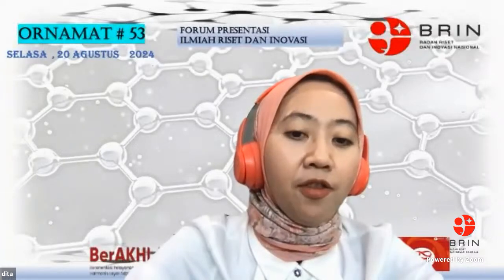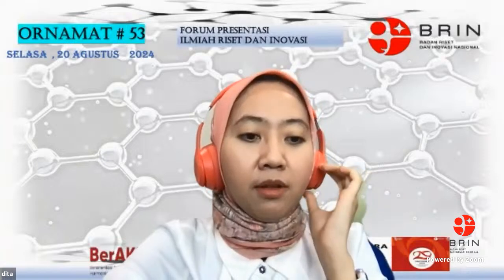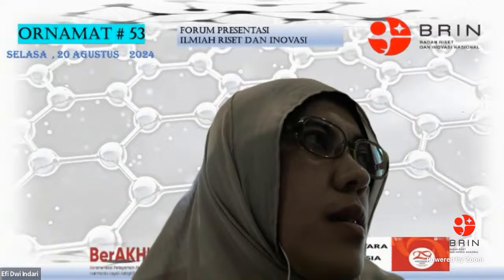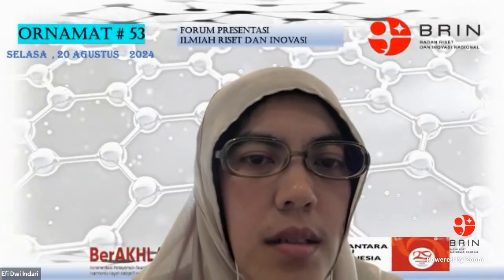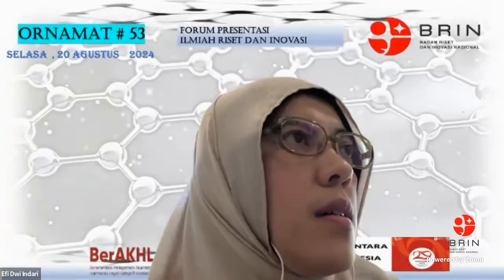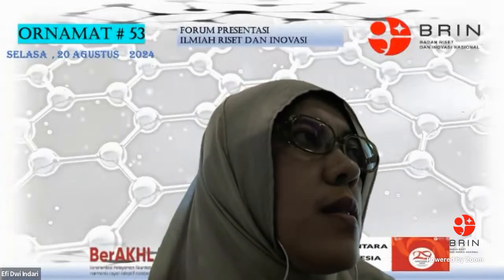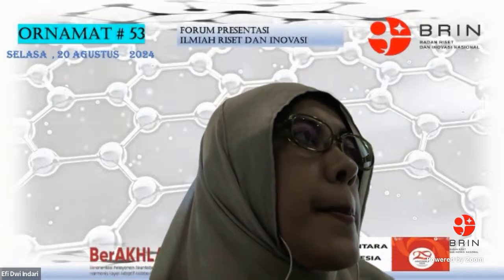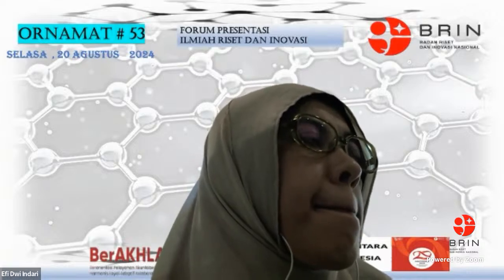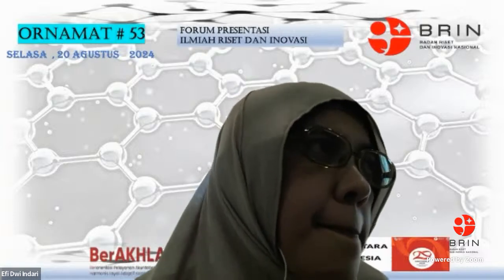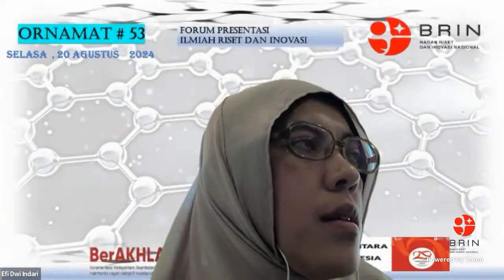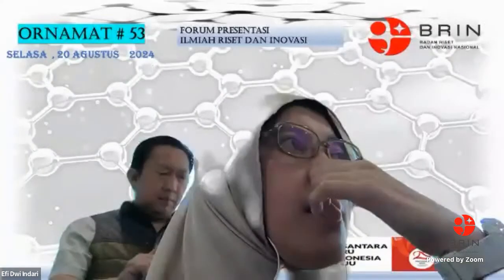Yeah, thank you very much. So we have a typical shape. One is the plate-like, or we have the needle-like. So we need to have the good shape. For the organic crystal, one of the advantages is that if we have the good conditions, we can reproduce the product and we can see by eye. But of course we need to check by XRD. The shape itself can easily be distinguished under the microscope. So reliability, one is XRD, we need to confirm, but then we can see the morphology, because it's very different. One is plate-like, the other one is needle-like, and the other one is rectangular.